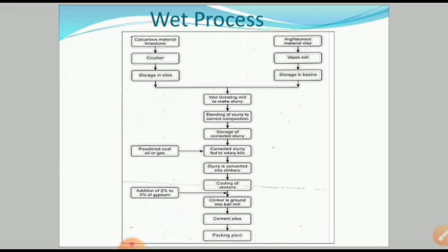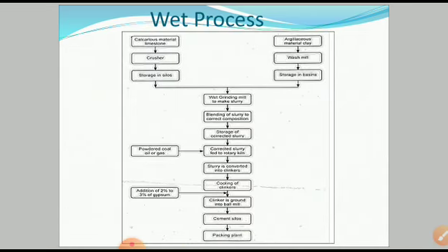The slurry is a liquid of creamy consistency with water of about 35 to 50%, wherein particles crushed to a fineness of Indian Standard Sieve number 9 are held in suspension.